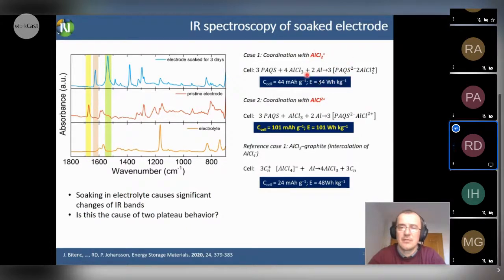And now if we calculate how much electrolyte we need to add for monovalent coordination, and also take into account the energy density of both electrodes, we come out with a very low number of 44 watt-hours per kilogram for the full cell configuration. And this is not the same type of calculation that Magali did, and I showed this at the beginning, where porosity is taken into account, and separators, current collectors, and so on. This is only on pure material.